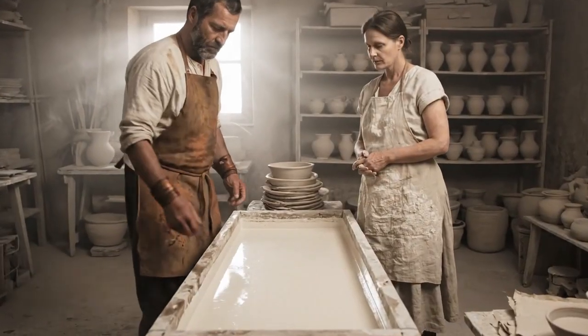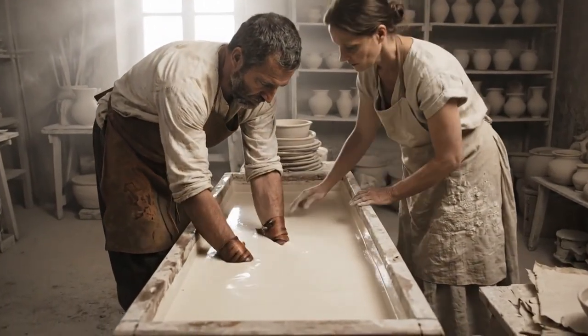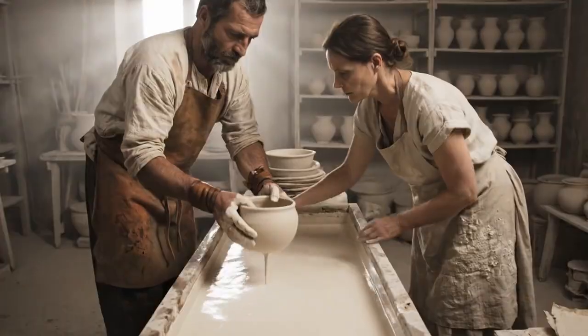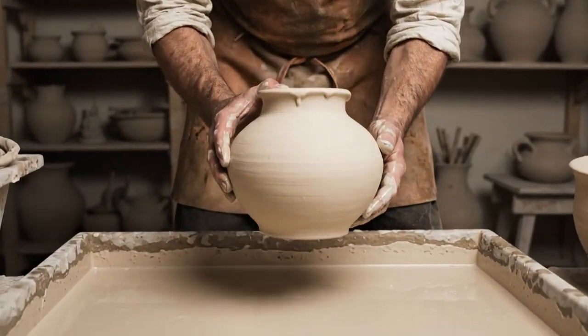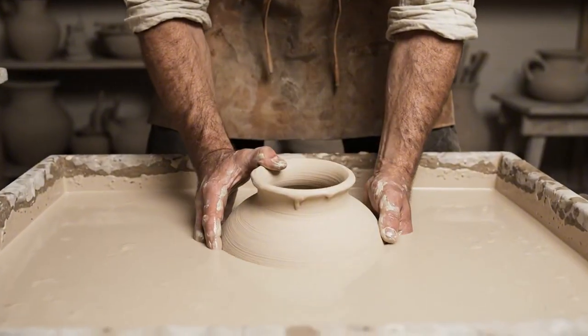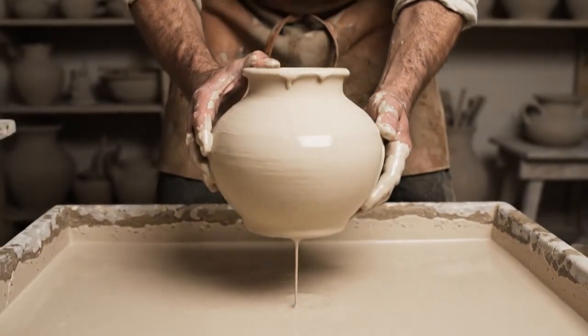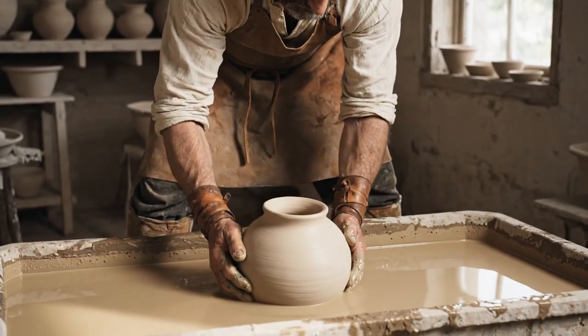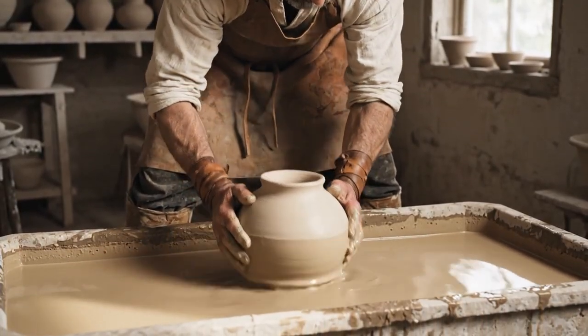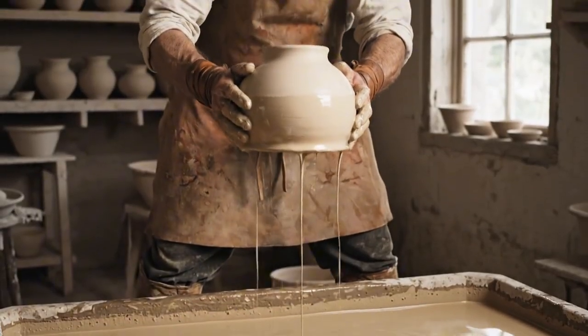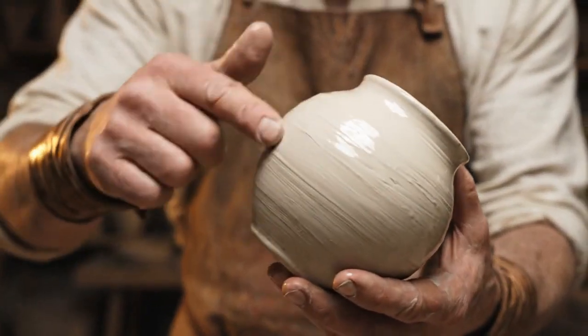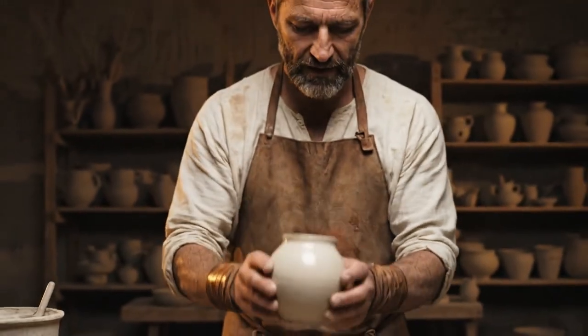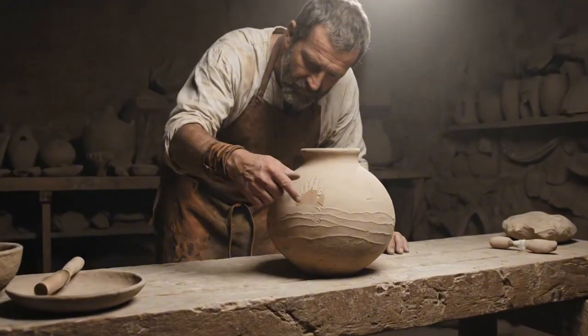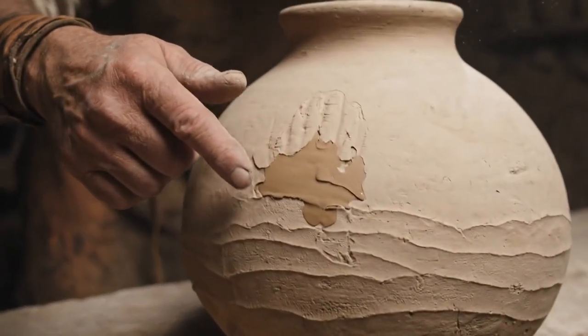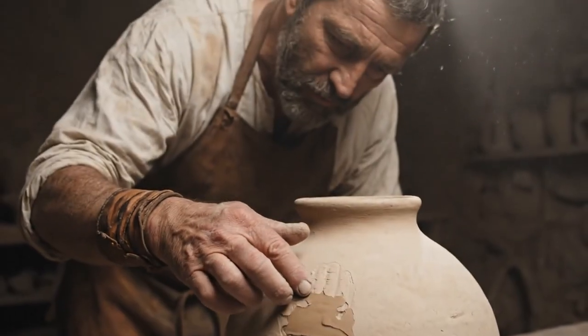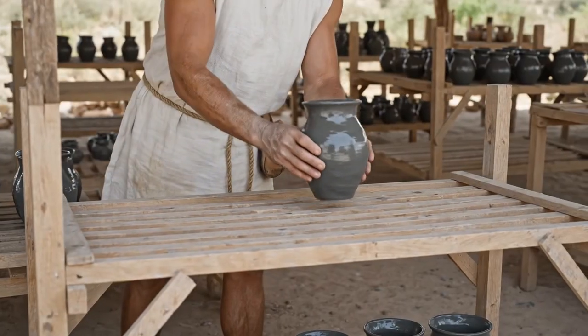The dried, trimmed, stamped vessel is carried to the dipping station, a long trough filled with the colloidal slip, harvested weeks earlier from the settling basins. The potter grips the vessel by its foot ring, inverts it, and plunges it smoothly into the slip, submerging it completely for a count of 2 or 3 heartbeats, then withdrawing it in a single fluid motion. The coating must be gossamer thin. A thick application will craze and flake after firing. On some surviving vessels, archaeologists can detect faint overlapping tide marks where the slip pooled slightly during dipping, evidence of real human hands working at speed.